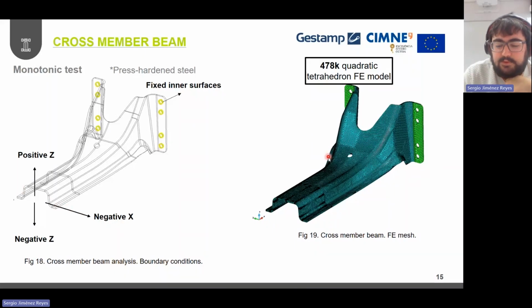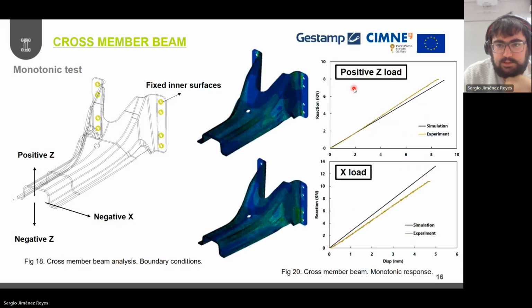This is the numerical model, the finite element model that we use to run these simulations, again using a quadratic tetrahedron finite element mesh. And these are the results obtained from the monotonic test and the comparison with respect to the experimental results, both in the positive Z direction and also when loading in the negative X direction.